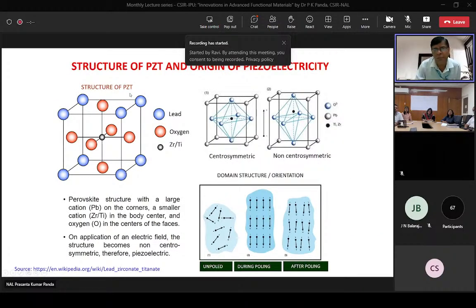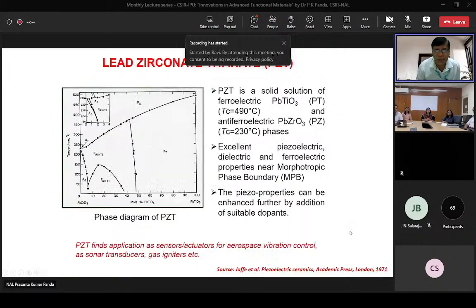Basically, PZT is a perovskite structure of ABO3 type. The lead and oxygen, which are bigger, are there, with lead at the corner and oxygen at the face-centered position. However, zirconium and titanium, which are very small because they are tetravalent cations, are in the center. It is a place to move up or down depending upon the electric field you apply. That's called poling voltage. Normally in an unpoled condition, the electric dipoles are randomly oriented, analogous to magnetic things. After poling, they will be aligned in one particular direction, and after poling this will remain.